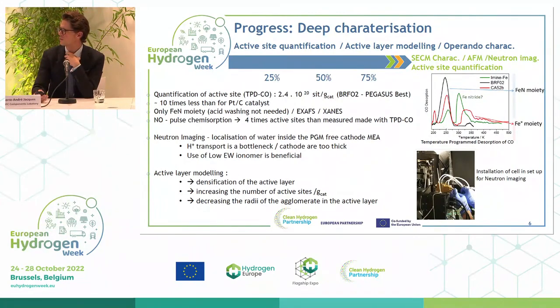Okay, and we also got an activity on modeling, and we modeled our active layers, and we can conclude that if you want to increase the performance of your active layers, of course you need to have a densification of the active sites, so more active sites in the same volume, in order to decrease the transport loss in the active layers. So we need to increase the number of active sites per gram of catalyst, of course, and we also need to work on the formulation of the ink and the preparation of the ink in order to break the big aggregates that we can have. So the smaller the size of the agglomerates and the aggregates, the better the performance of the active layer.